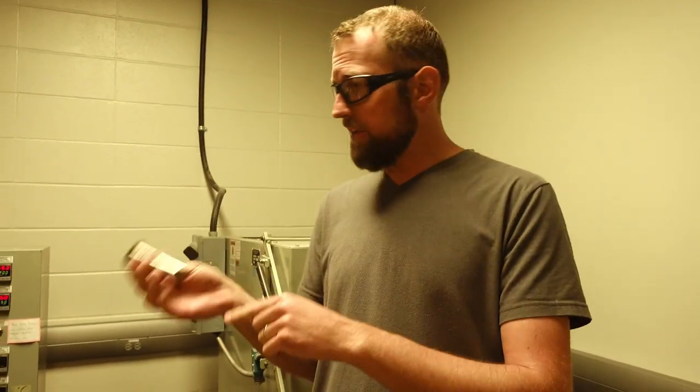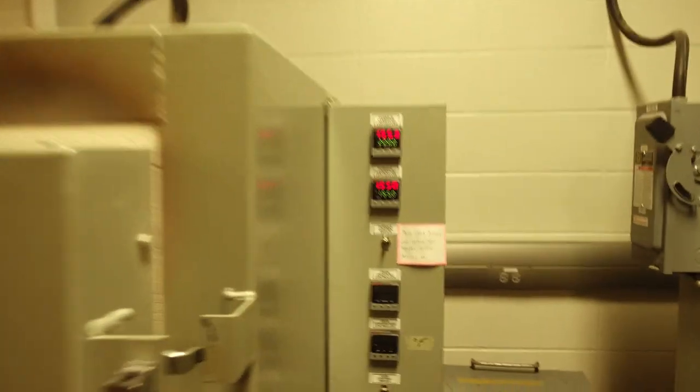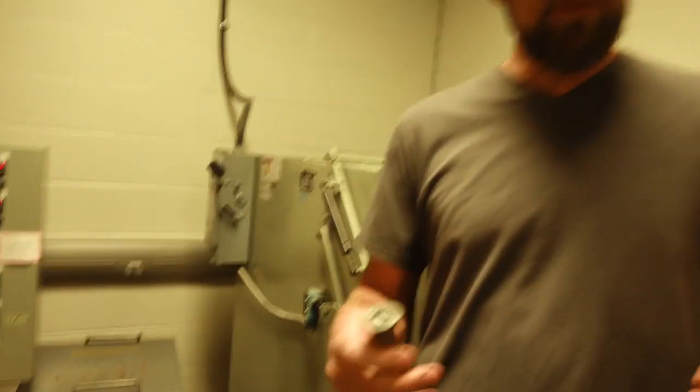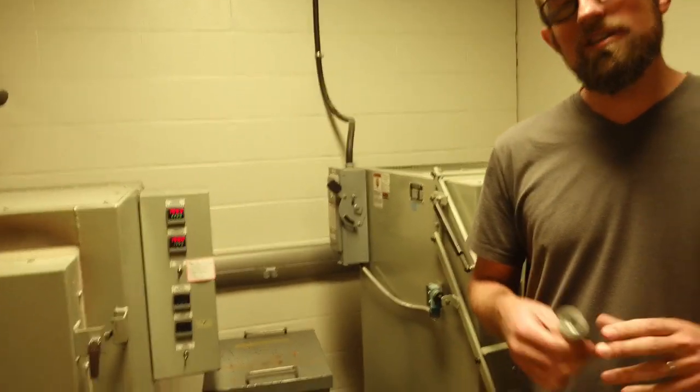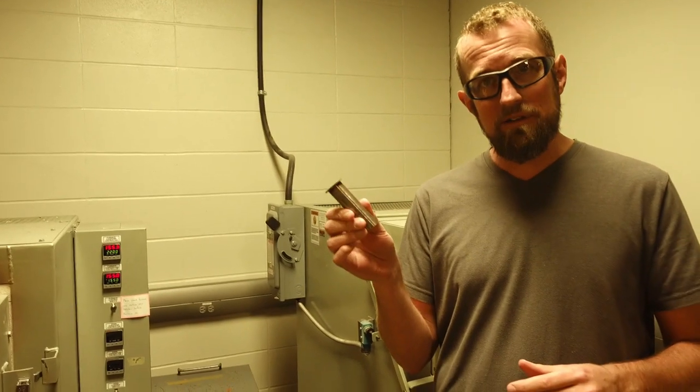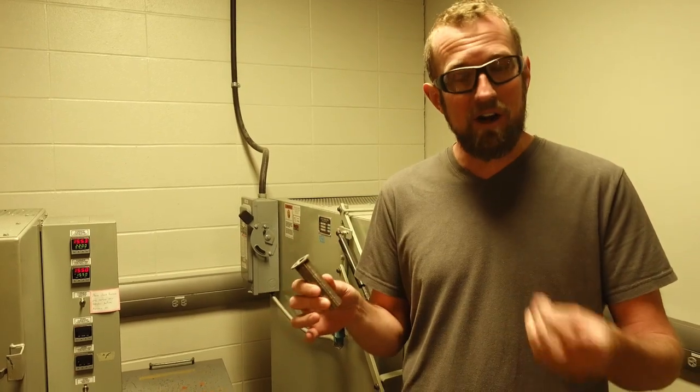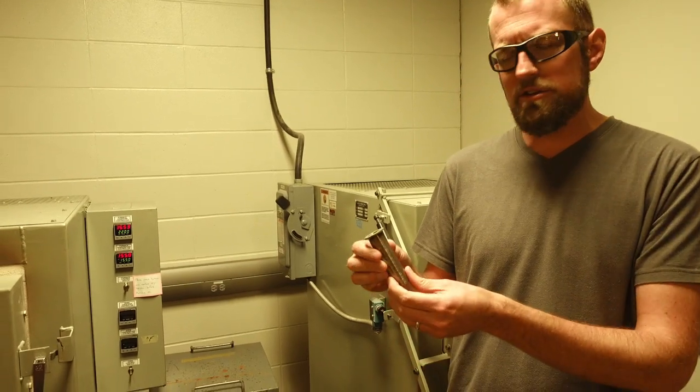The idea is that I'm going to put this into the furnace here at 1550 degrees Fahrenheit, so that's 843 degrees Celsius. It's a nice bright red hot that we're going to bring it up to. And once I get it up to that temperature, all of the carbon should be dissolved in here. It should fully form into austenite. Dissolving all the carbon and allowing me to quench it to form that martensite or slow cool it to form the ferrite that we looked at a second ago too.